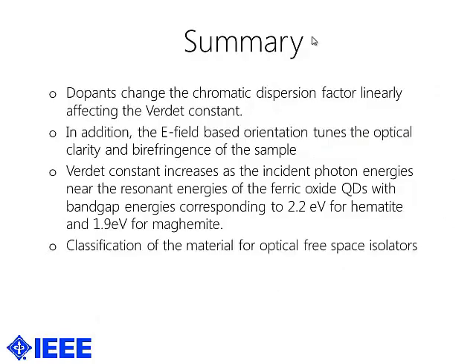Now, in summary, we found that the dopants that we used changed the chromatic dispersion factor, and they were linearly affecting the Verdet constant in accordance with Henry Becquerel's equation. In addition, the electric field-based orientation of these nanoparticles tunes the optical clarity and birefringence of the sample. Now, this has been substantiated, and more evidence is given in one of my other papers, which are not included in this study. And the Verdet constant increases as the incident photon energies have more proximity towards the resonant energies. And like I mentioned, for hematite it was about 2.2 electron volts, and for maghemite it was about 1.9 electron volts.